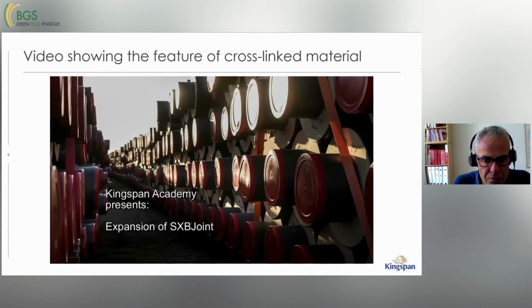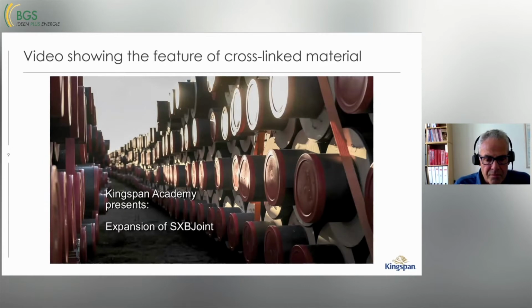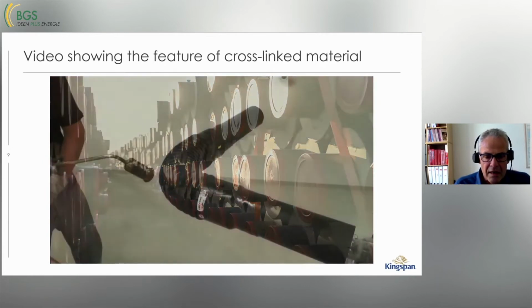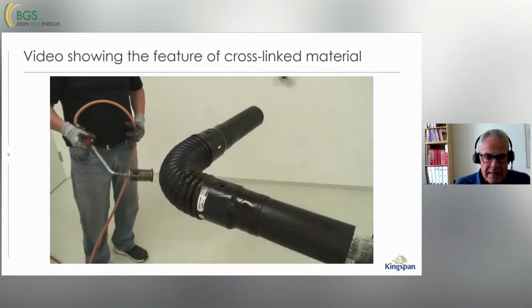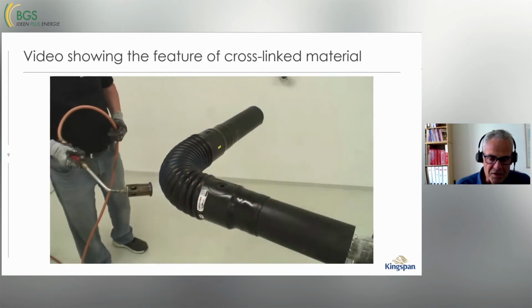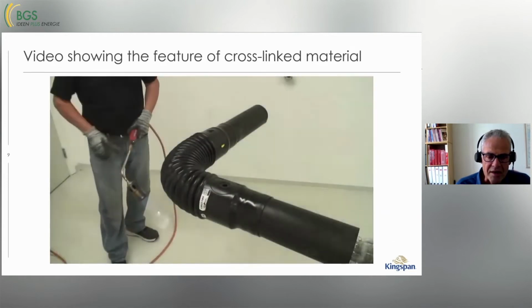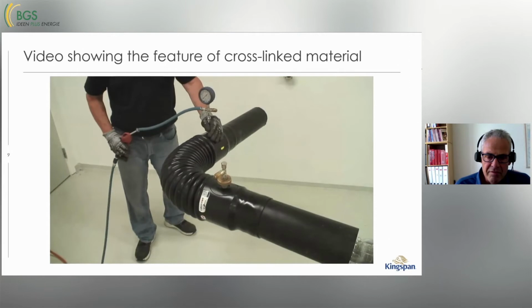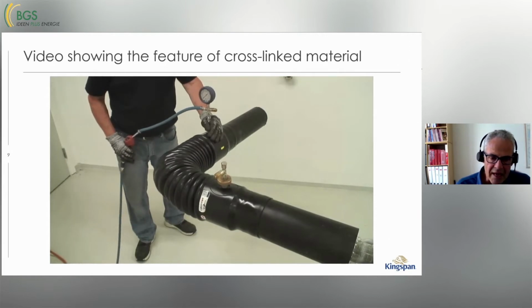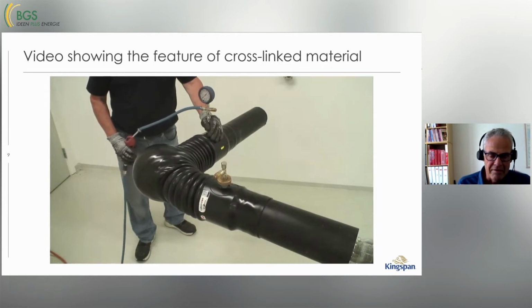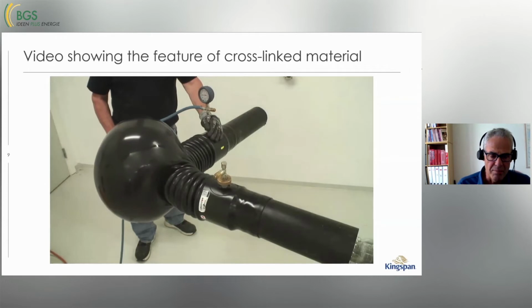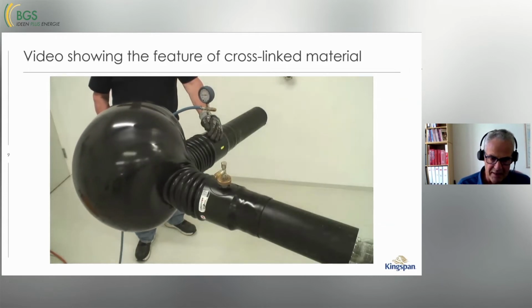Then I have 2 videos that actually, better than words, explain the features of the cross-linked casing joints. The first video is a video where we will heat up a place on the cross-linked material, and we will overheat it so that it becomes very, very soft. Then we will put air pressure to the casing joint, and it will start to expand in this area where it's very hot and very soft. And we will expand it to the extreme, so the material gets extremely thin, like paper.